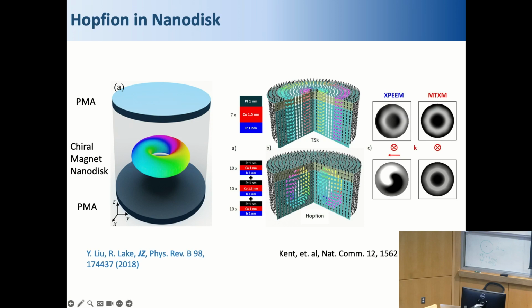Sorry, yeah. So you need two kinds of anisotropy. One is the PMA, and in the middle, you need what kind of anisotropy? In the middle, you don't need to do anything. It's just an iron germanium nanodisk with a fine-tuned thickness. So the complexity is introduced by adding the surface anisotropy. Yeah, because you need to polarize the spins far away from the center to the same direction. So that's why we artificially